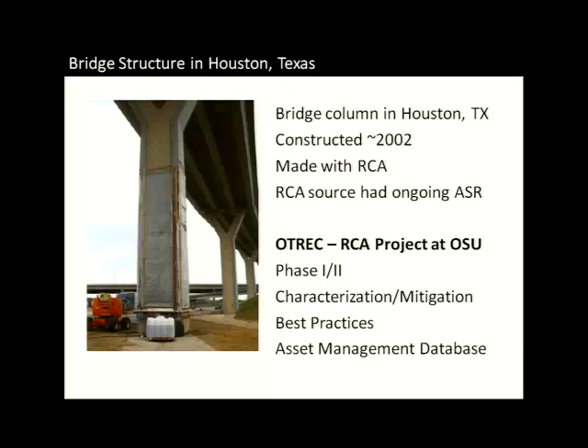So one of the things that has come out of this is a research project that we now have at Oregon State looking at characterizing recycled concrete aggregate sources so that we can make sure we have the right testing methods in place to avoid this type of reaction from occurring in new concrete. As a side note, Texas has since banned the use of recycled concrete aggregate in new concrete, so that you can only use it as a non-structural fill material, or it's landfilled.